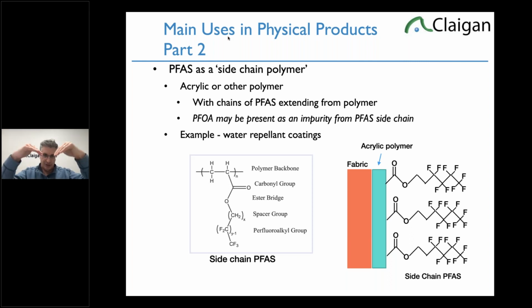During the manufacturing process, that ester, the O, can break, and you have one in a million of these loose, and some of them will become like PFOA or whatever its length is. So there's a possibility when this chemical is manufactured to have some residual PFOA, and it's really an impurity because the PFAS side chain can fall apart. They can actually filter that out, and they can move to shorter chains. Now, the reason why this is so water repellent again is the outside of the fabric, what the person is touching, or the outside environment, is a fluorocarbon.